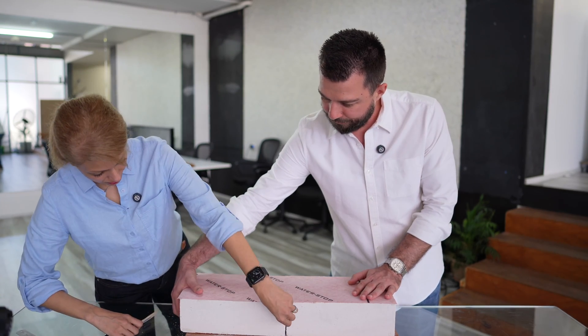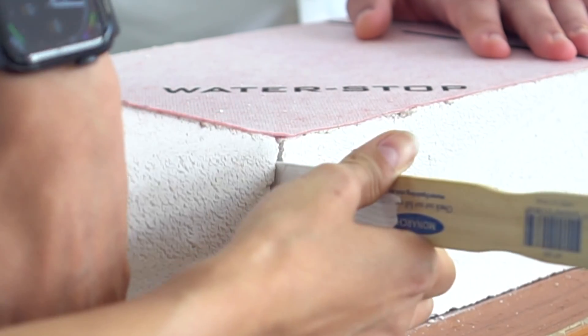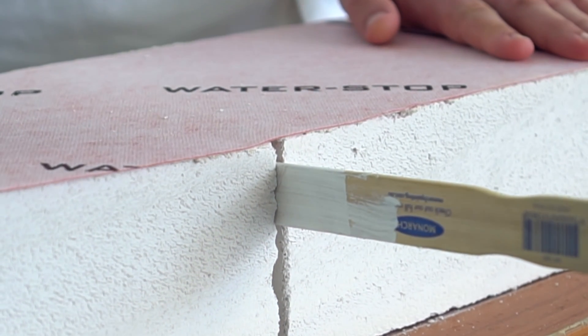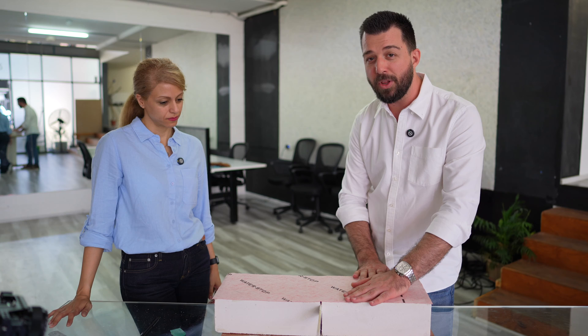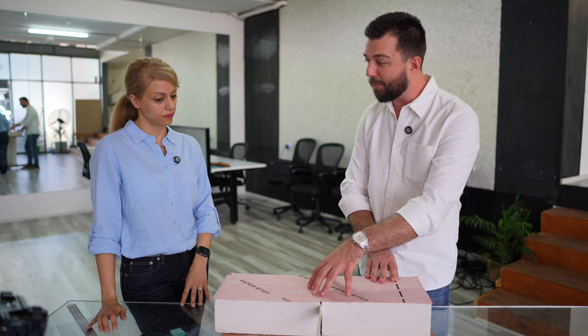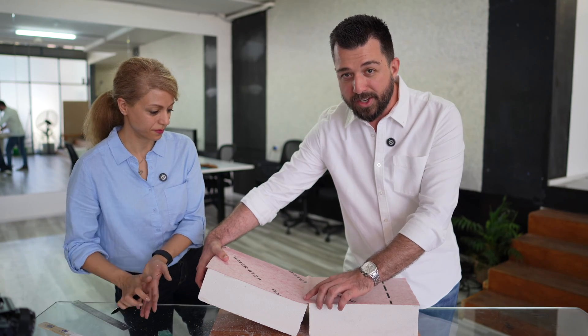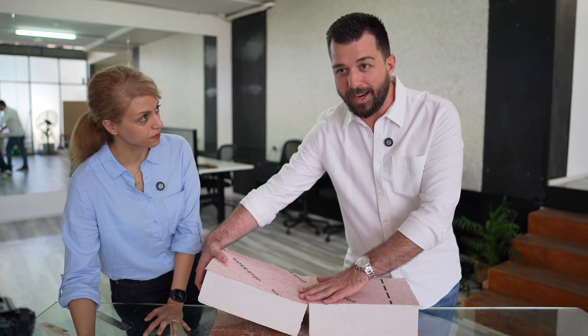So this one's a five mil. We've now got the five millimeter spacer — taken from zero millimeter joint at installation time to five millimeters. I did hear a small amount of — not tearing — but debonding occurring. That's exactly what I'm expecting to happen: a product with very high tensile strength is going to hold itself together, and instead of wanting to elongate or crack, it might debond a little from the substrate and move. You can see a little bit of a ripple here — that's where the membrane has debonded, where this ripple's occurring. And that's exactly as intended.